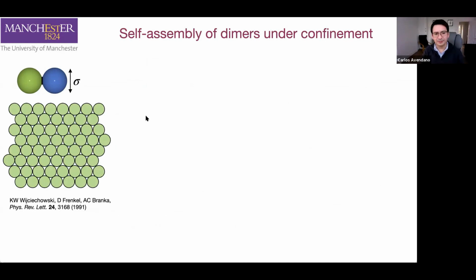That's an interesting system because the intuition is that the packing of this system should be very similar to that of spheres. Why? Because the particles are made of two spheres just bonded together. But something interesting happens in reality. In 2 dimensions, we have these dimers, and they have different possibilities to arrange. The individual spheres will pack almost exactly the same, but now it depends on how the orientation of the particles takes place.